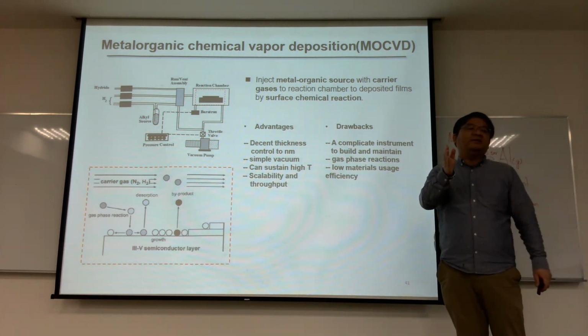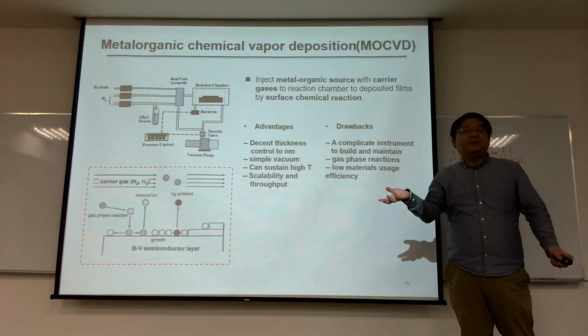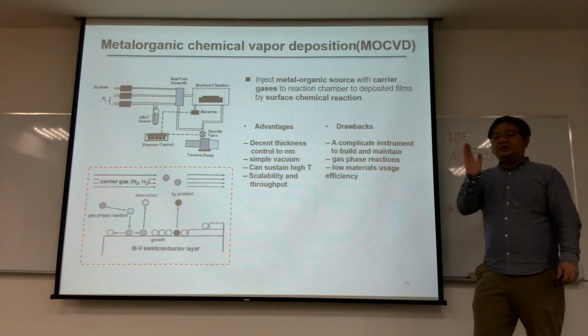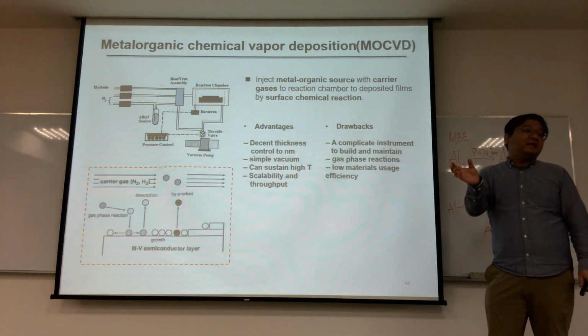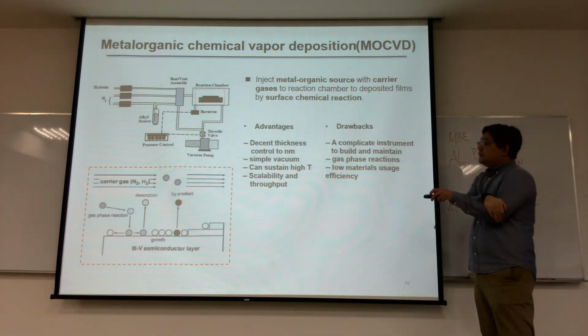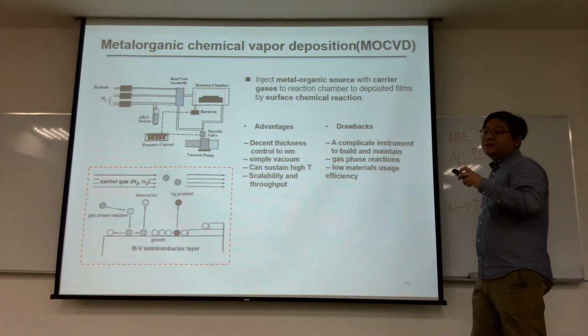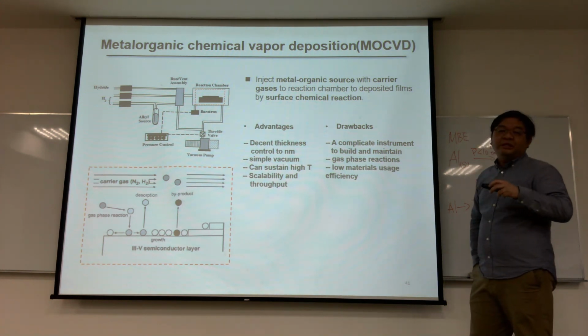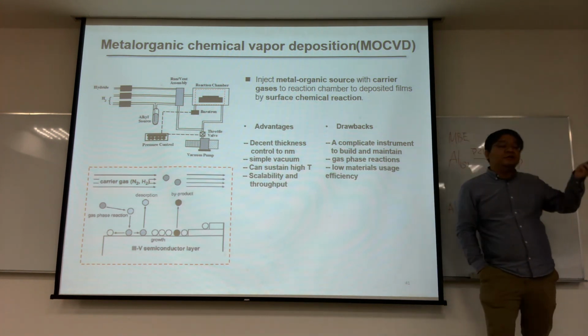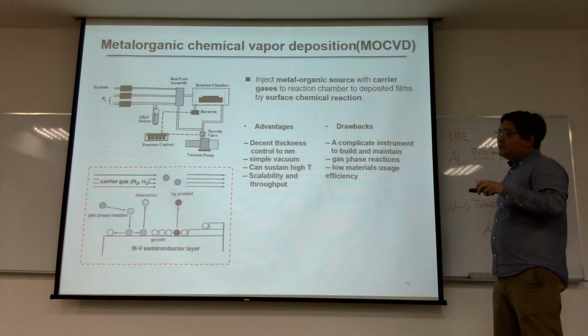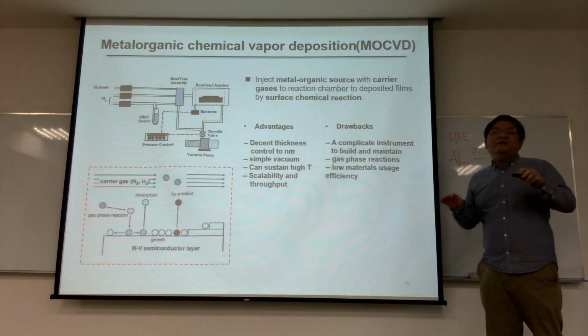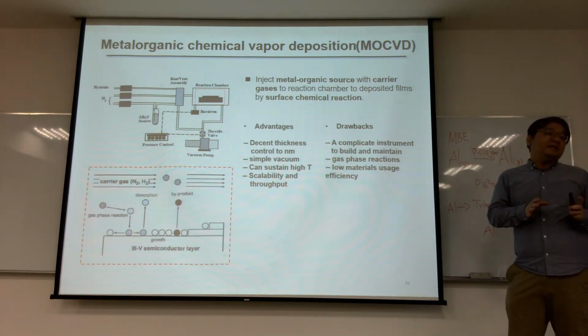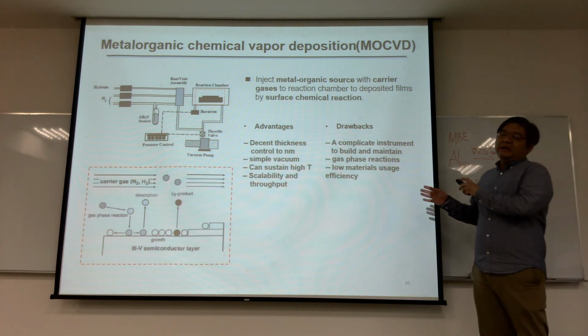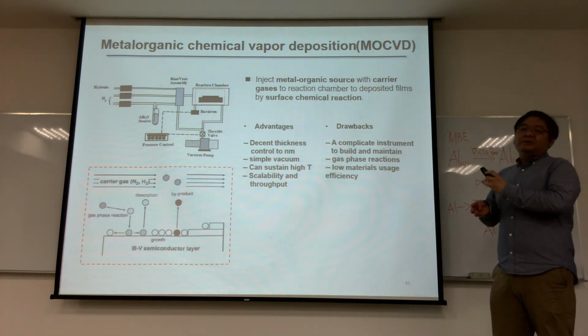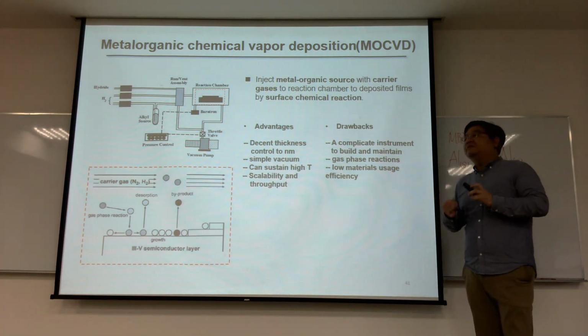For example, if you want to do it with LPE, you need to cut the time to one thousandth of a second. That's practically impossible. But when you are growing with MOCVD, you can control your time at probably 10 seconds, 20 seconds. That's practically possible. So we can still do a pretty decent control of the growth speed. With pretty decent thickness control, you can have a delicate structure in your epitaxy. Basically it balances the good and the bad between LPE and MBE. It has a decent growth rate, good precision, and everything is fine for practical use.